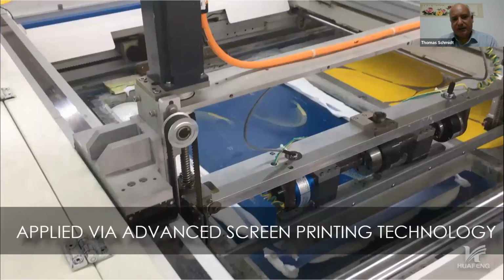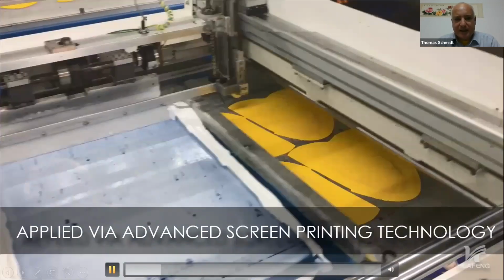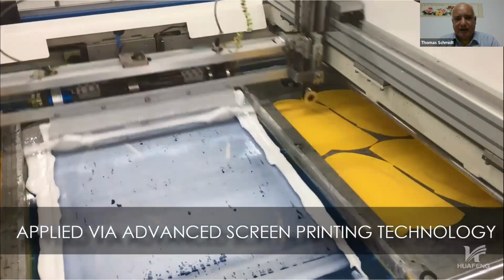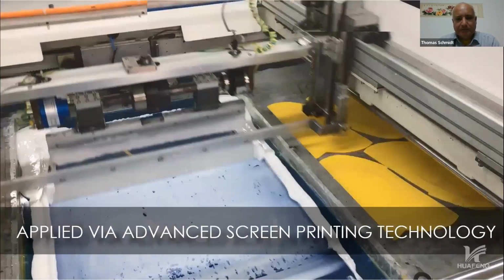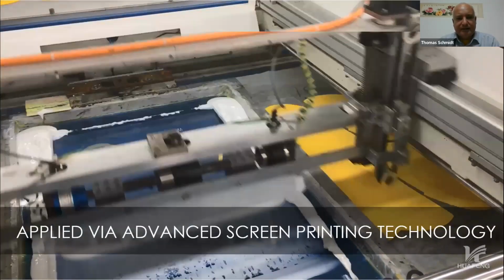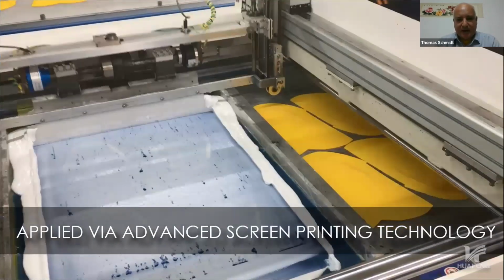And this is how we do it in production. This is a little video. I can switch it on for you. So this is an automatic screen printing process where the screens are moving along a long table. And the ink, in this case the base coat, is applied directly onto the mesh. It's an advanced screen printing technology because our screens are able to deposit very high coating thickness. Already with every shot we print, we can deposit a very thick layer.